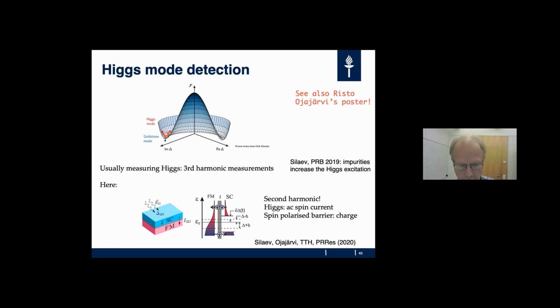So you apply an AC field and study what happens at three times the AC frequency. Now what we basically saw is that if you have a spin split superconductor, you actually get access to the Higgs mode already from the second harmonic, and what the Higgs mode actually drives is an AC spin current.